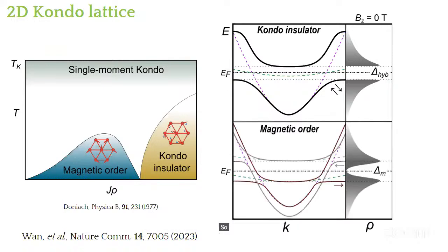So these two bands are hybridized, and basically we are in front of a Kondo insulator regime. The magnetic order is similar, but it's not the same. There's interaction between these two bands as well, and new bands arise from this. There is an increase of the density of states at the Fermi level. There is basically the formation of a gap-like feature as well around the Fermi level. So these two are pretty much the same, okay?